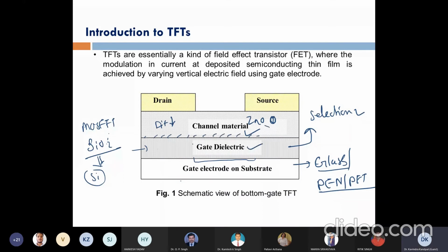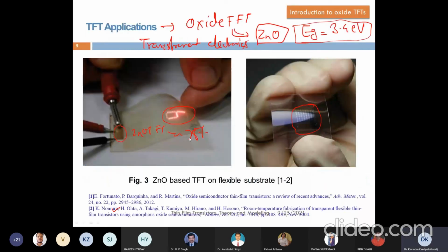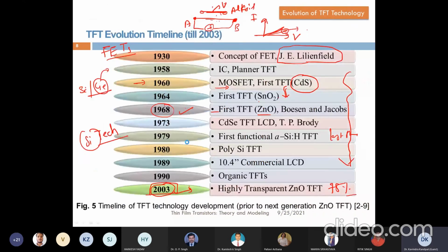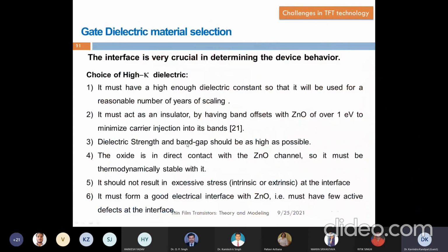Because whenever you make a transistor, the most important thing is basically the interface. The interface needs to be very pure, very clean, right? There should not be many dangling bonds, because if there is less DIT, then only if you apply a voltage will it be able to modulate the carrier density underlying the channel material. So that is the one thing you need to find out. Once you do the selection, you will identify there are lots of candidates for the gate dielectric. Based upon these properties, which can provide a good gate dielectric with a small number of interface states, what the leakage should be is another criterion.